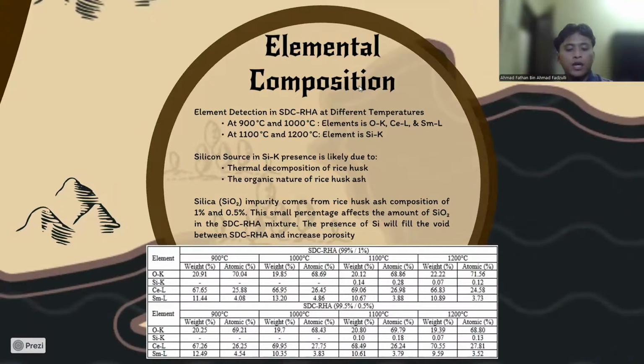EDX, elemental composition. EDX analysis reveals how temperature and RHA content orchestrate the elemental symphony in our SDC RHA composites. Let's see the patterns. There are 2 distinct regimes. First is at 900 Celsius and 1000 Celsius. The present elements are O K, Ce L, and Sm L. At 1100 Celsius and 1200 Celsius, the element Si K appears. The silicon source in Si K is likely due to thermal decomposition of rice husk.